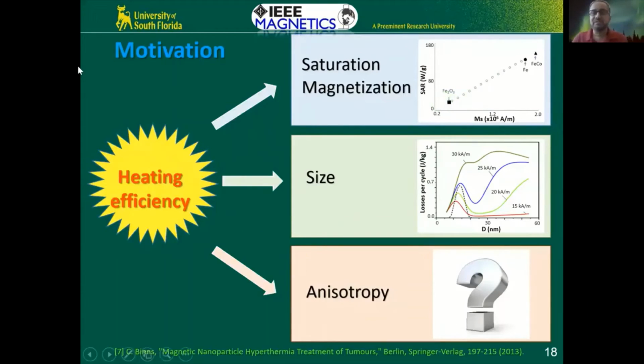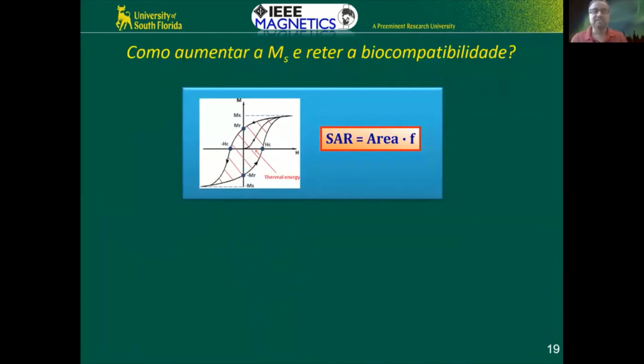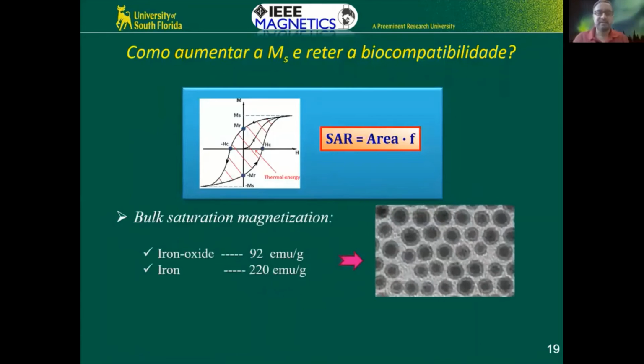Okay, but first, when we saw this one right here, we thought of an idea. We thought, okay, how about fooling the cells? How about fooling the cells by making a core shell nanoparticle with the core being iron, which has a large saturation magnetization, and the thin shell completely covering the iron being an oxide, magnetite, which is known to be biocompatible. So in other words, we try to make these iron core, iron oxide shell nanoparticles.